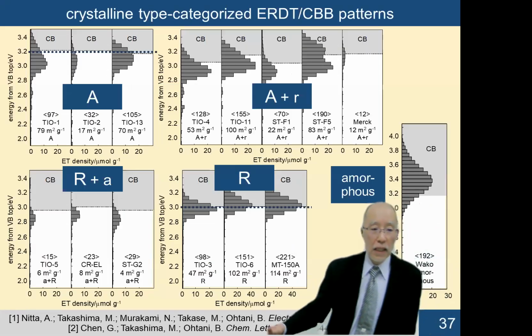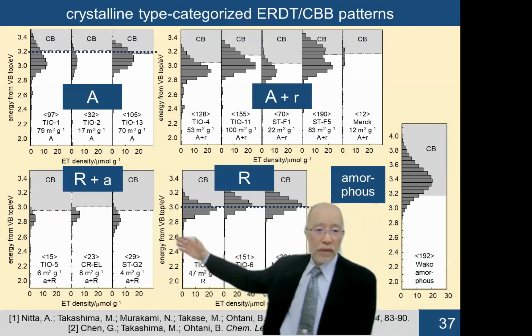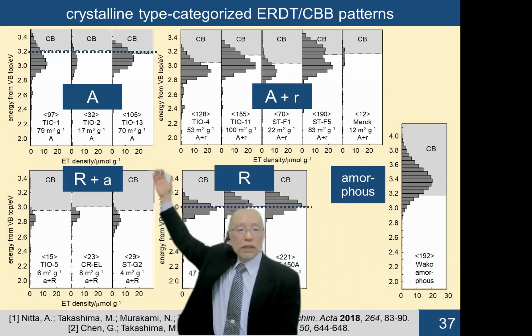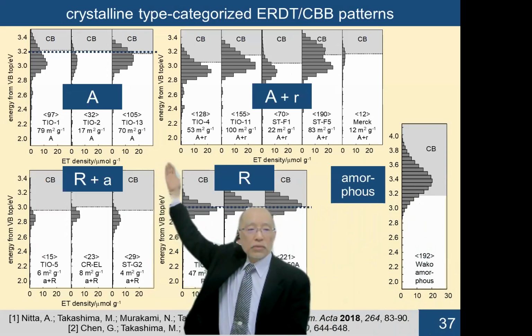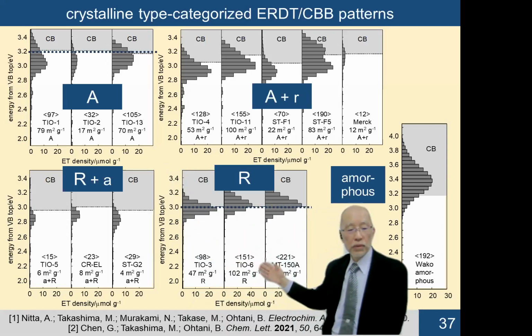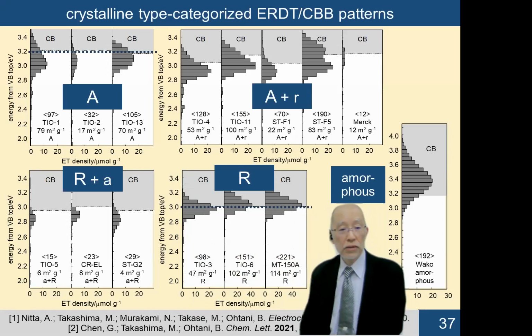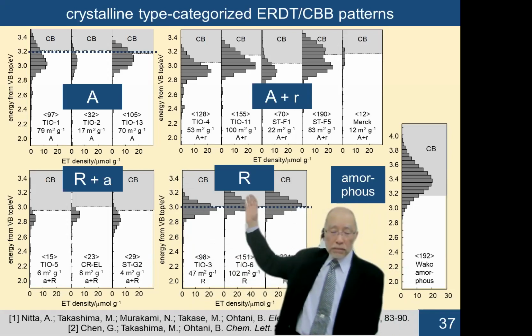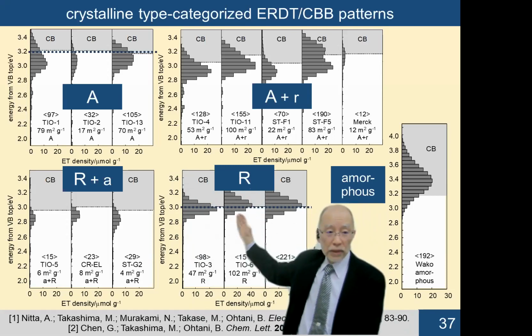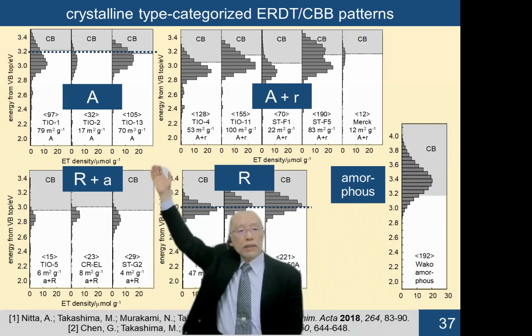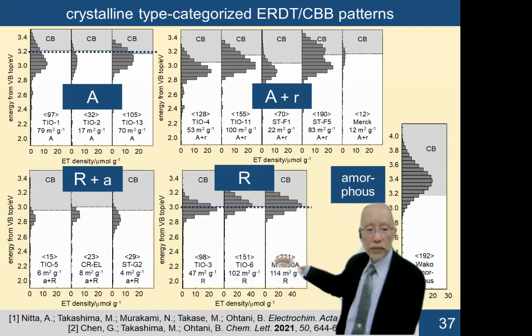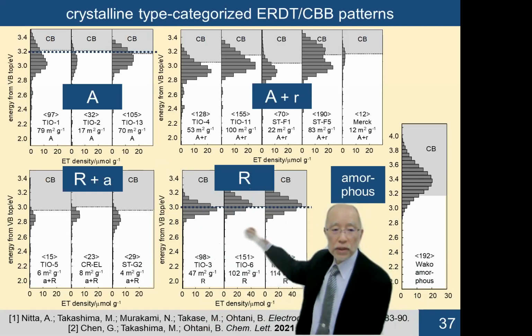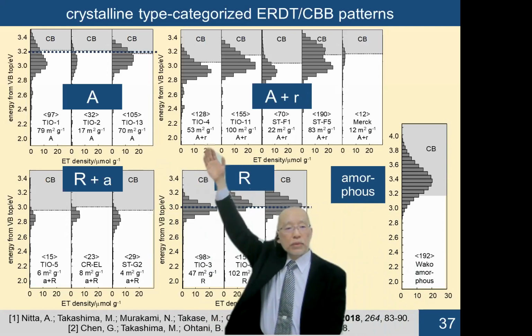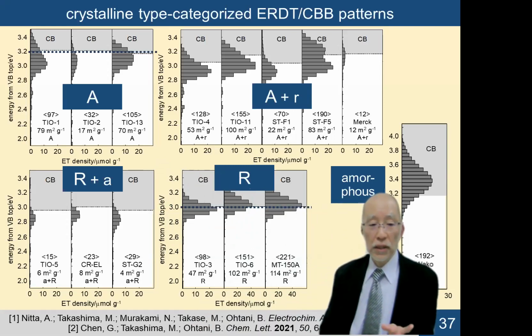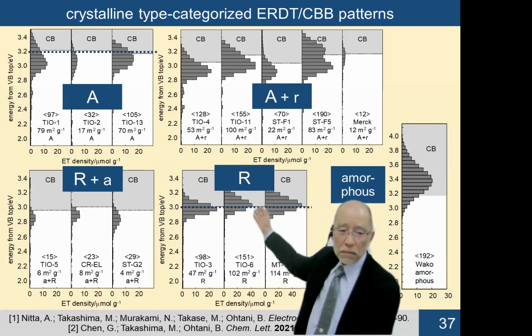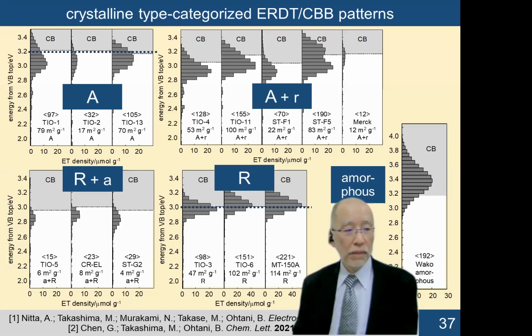Okay, going back. This is only part of the results. A means from the XRD result, only anatase is included, three samples. And for rutile, three samples, only rutile structure is given by XRD. Sorry, the CBB position for rutile is about 3.0, and for anatase, that is 3.2. Even if different samples are used, if the bulk structure is the same, the positions 3.0 and 3.2 are the same. So that suggests that the CBB position depends only on bulk structure, not surface structure.